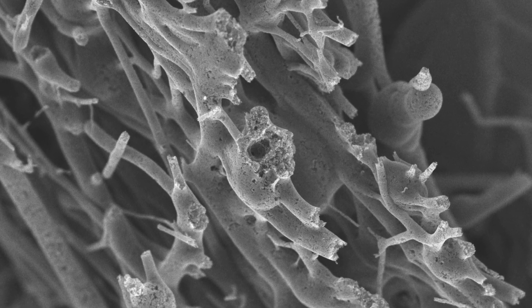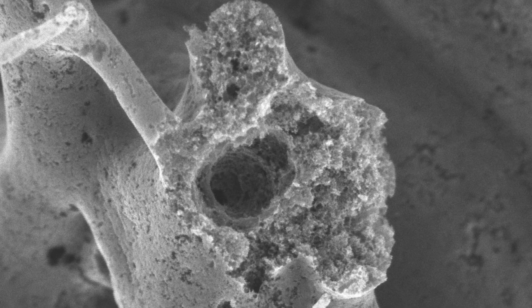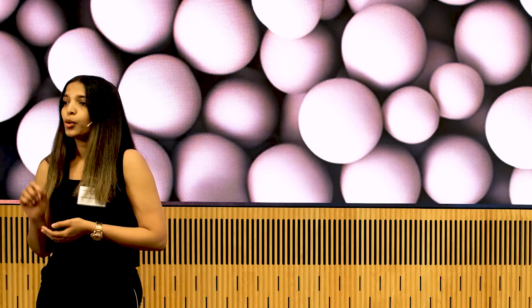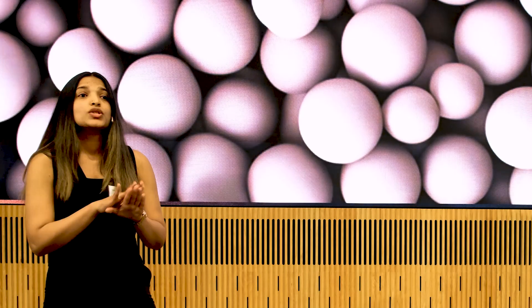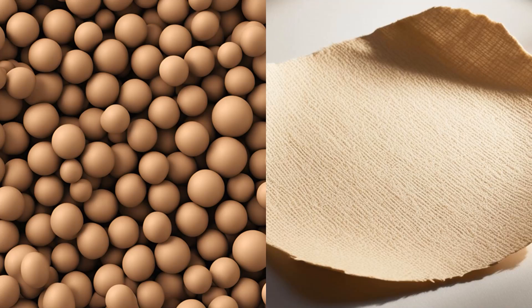But beyond that, what if we could use them as such as separation membranes? Structural integrity could be a problem. To tackle this, here comes our third component: lignin nanoparticles formed by solvent shifting method, or simply switching solvents. With a high surface area, we can easily functionalize them, making them suitable for a wide range of applications. Among these, I chose nature's own enzymes for functionalization. Combining lignin nanoparticles and lignin nanofibers opens the door for advanced separation membranes, where lignin nanoparticles are functionalized with enzymes and lignin nanofibers stabilize them by preventing enzyme leaching.